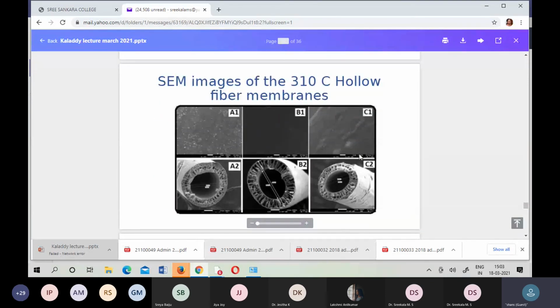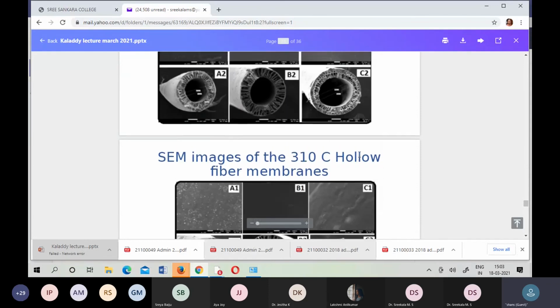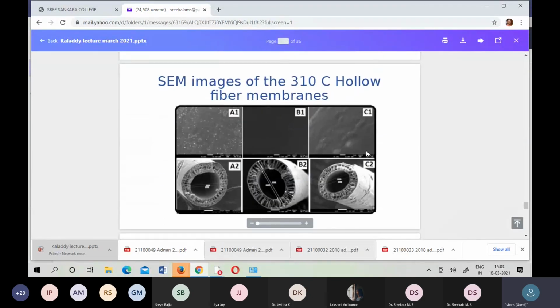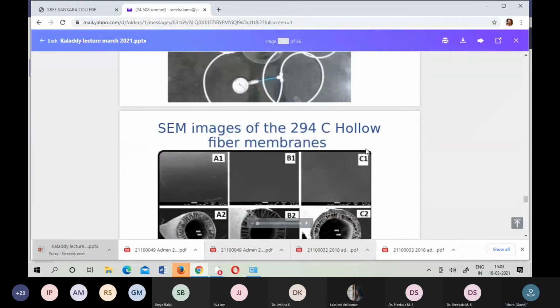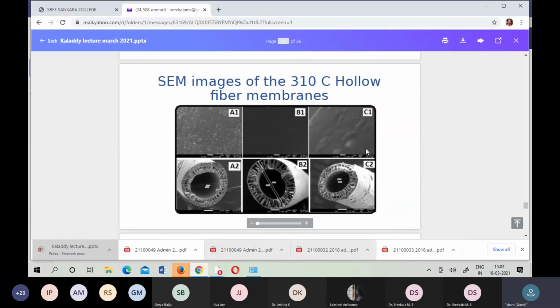See, when you're doing the cross section, the outer diameter, inner diameter, everything we matched. But these spiral channels, the channels of different structures, we are getting. Then this is after coating. What we did, this C1 shows the coating. So something was on the surface of the polyacrylonitrile membrane, but the cross section is retained. There is no change because we are doing the coating on the surface of the membrane, not inside the membrane. So the cross section is retained. Only the membrane surface was a little bit changed, or more dense, I can see, because of the chitosan coating.